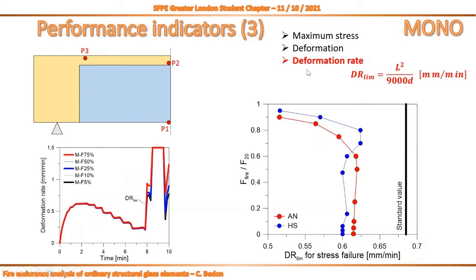So let's try to check what happens in terms of deformation rate and no more deformation only. Also in this case, we take a reference limit value from standards. What happens again is that we cannot see strong modifications in the deformation rate as a function of exposure time, even when we did increase the mechanical load at midspan. But okay, what can we say as a general conclusion for deformation rate parameters? We can say that the effect of glass type, annealed compared to heat strengthened, has a very small effect for the global deformation analysis.